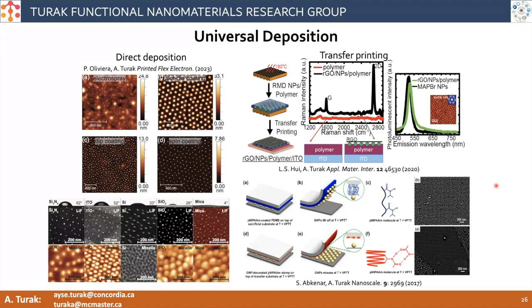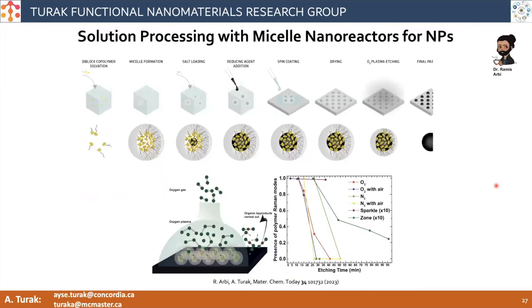Not only that, we've also developed a number of transfer printing techniques, so we can take the nanoparticles off of a sacrificial surface and then put them on, for example, a polymer or other kinds of structures, to make these kinds of graphene nanoparticle composites, in order to move the particles around from various surfaces. Right, so the final step that we usually use, and this is the one that can be a little tricky because not every material is able to withstand this process, is oxygen plasma etching, which we would normally use as our last step to remove the polymer from the surface.